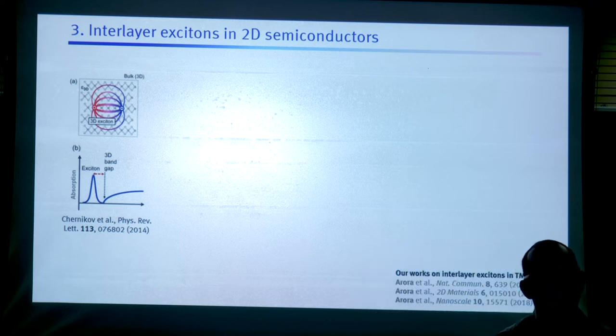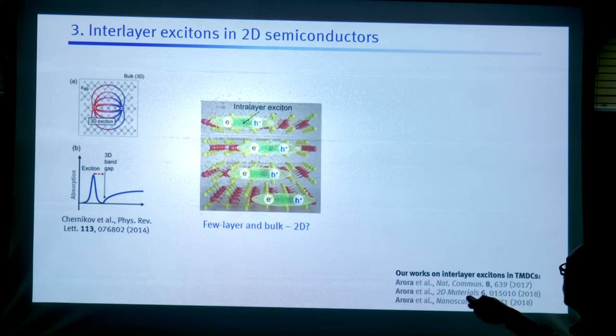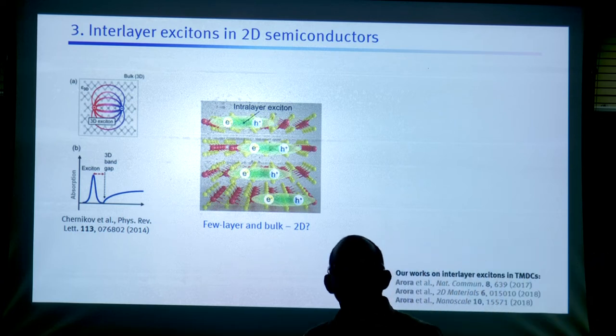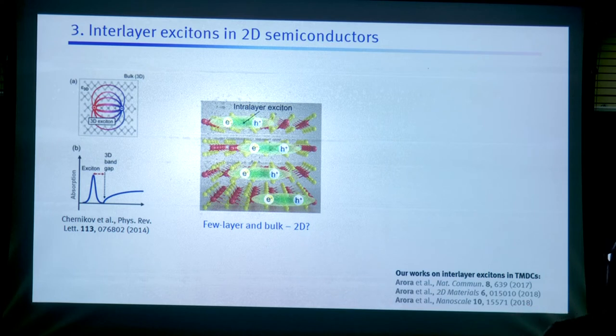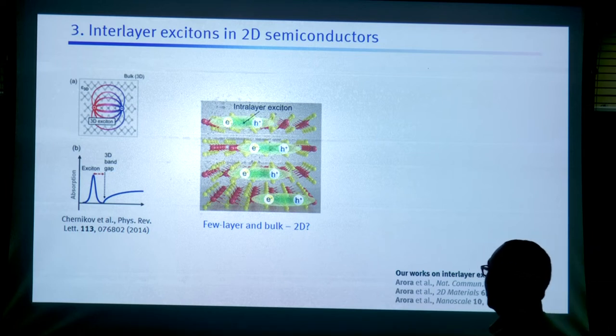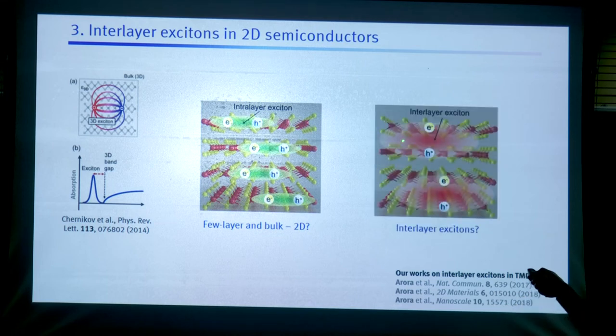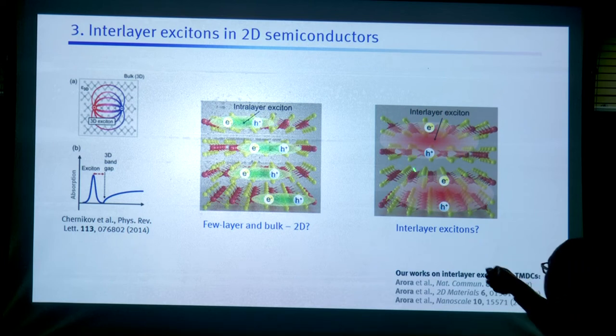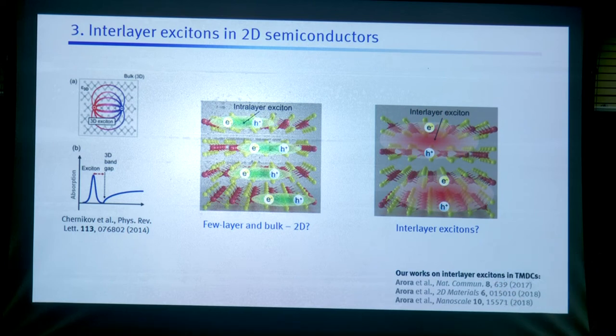So we set out to check this: if the bulk should be 2D, what should be the signatures? Well, I'll tell you. First, you should have intralayer excitons, meaning excitons which are just confined within layers. People were all working with monolayers, and we were also working with monolayers, but if we are able to study two-dimensional physics just with bulk material, that should be very nice, because bulk materials are available everywhere. You don't have to do much more than peel very thin layers off. So there should be intralayer excitons, and there should be interlayer excitons as well, because now electrons and holes should lie in the neighboring layers, and there could be excitonic interactions, which are Coulomb-like, between neighboring layers.